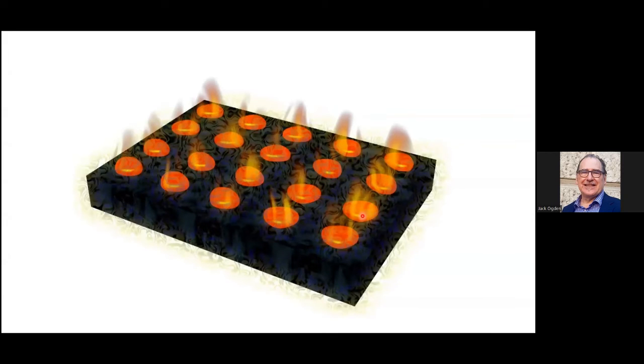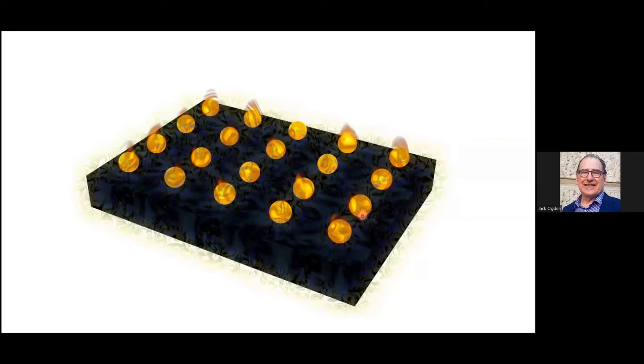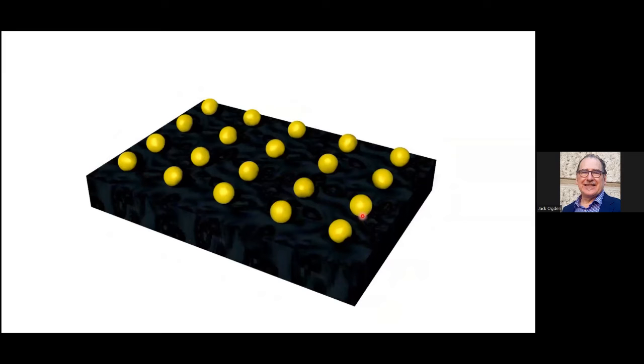and they melt. And when they melt, they roll into little balls. This is surface tension. There's no skill involved. This is just surface tension makes them roll into balls, and they cool down, and you've got your grains. Now, if you're making a big pair of earrings, you might need several thousand of these. So it takes time, but it's not complicated. It's time-consuming, but not complicated.